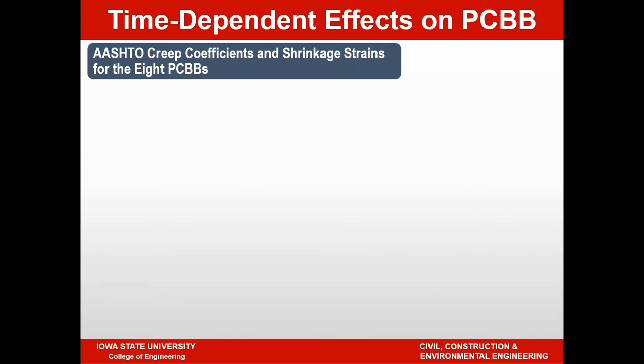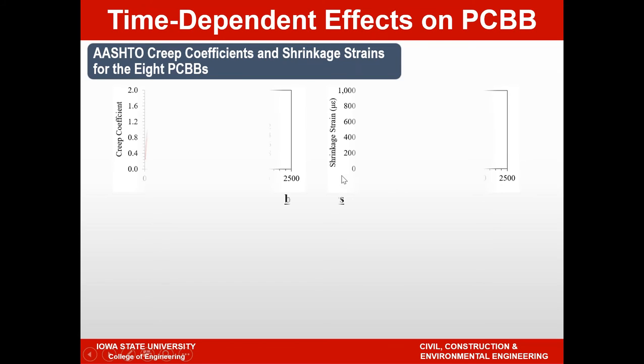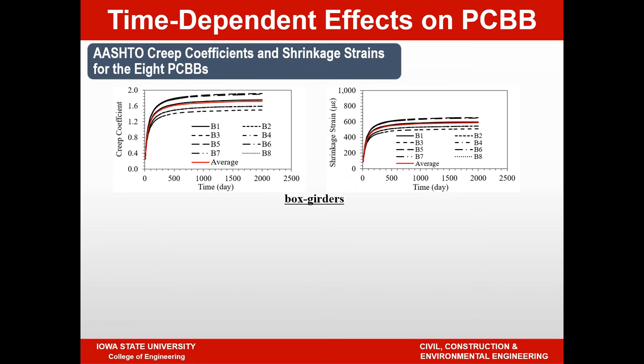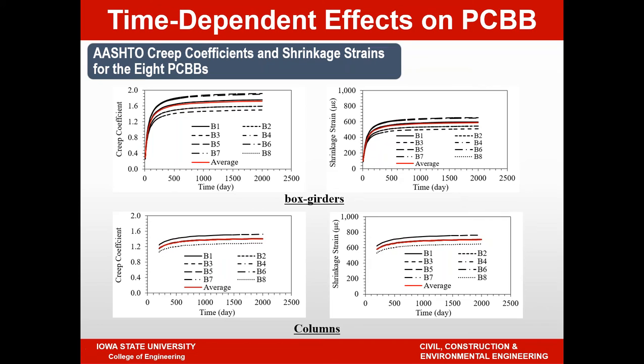For the analysis, we used the AASHTO creep coefficients and shrinkage strains. And this one shows the creep and shrinkage strains calculated for different bridges. And in each of the cases, once we calculate the strains and creep coefficients, we also looked at the average value. So this one shows what AASHTO recommended value for each and every case is, and this one shows the recommended values for the columns.